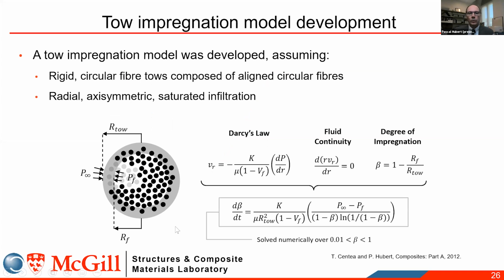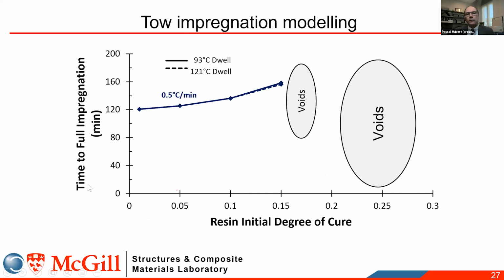We have some wonderful work that has been done over the years on that topic, and we can integrate those analytical equations and obtain a solution for the level of impregnation of the tow as a function of our material properties, the permeability, viscosity of the resin, and so on, and our boundary conditions in terms of compaction pressure and bag pressure.